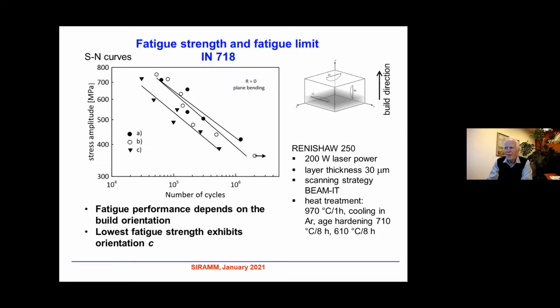Okay. And also the threshold value is dependent on the microstructure, I've seen. Yes, the threshold value depends on the microstructure, because the crack propagates by processes in the plastic zone. And you could imagine that if the microstructure is different, then the processes in the plastic zone are different. For example, in this Inconel, there is a tendency to build long fatigue bands, and it depends then on the movement of dislocations and so on. So the microstructure critically influences the threshold values.